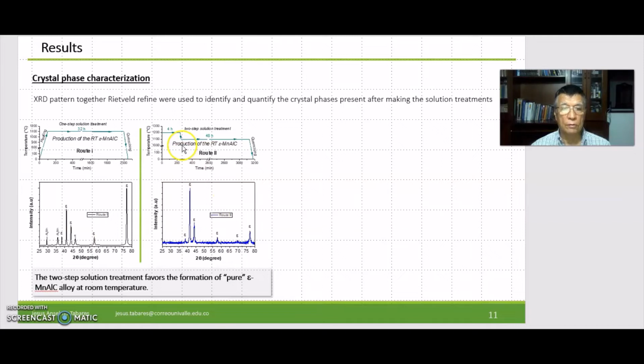Route 2 achieved production of a virtually pure epsilon phase according to Rietveld refinement that is not shown here. Thus, we found the two-step solution treatment favors the formation of a virtually pure epsilon manganese aluminum carbon alloy at room temperature.